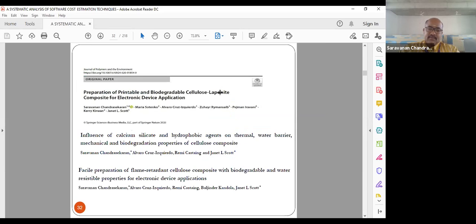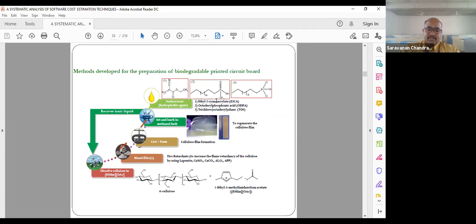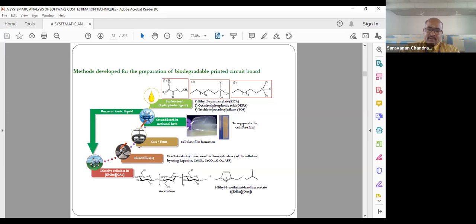Based on that, we have recently published one paper, and other papers are in the pipeline. This is the entire process. First, we dissolve the cellulose in ionic liquid. We added flame retardants into that in order to increase the flame retardancy. We made a film, and then we removed the ionic liquid. We recovered it, and we can reuse it several times. Also, there is a hydrophobic agent, which is surface treated to increase the water barrier property. Also, the surface is more suitable for printing.